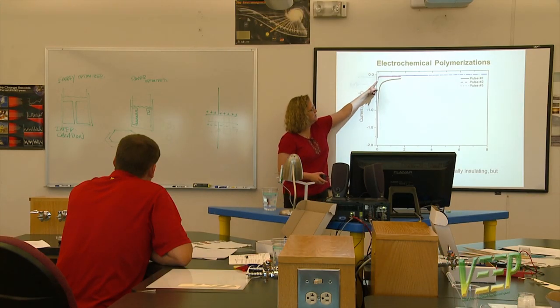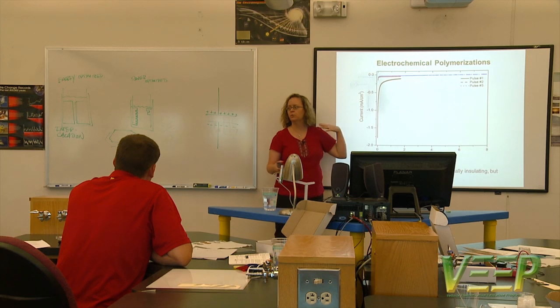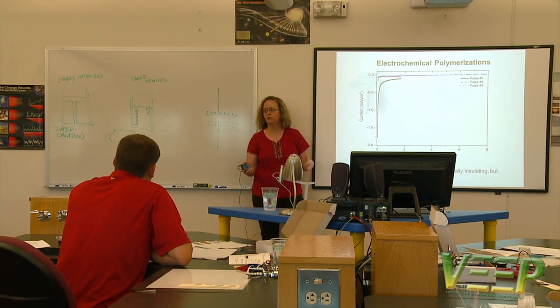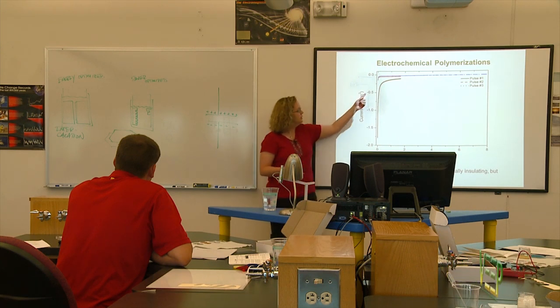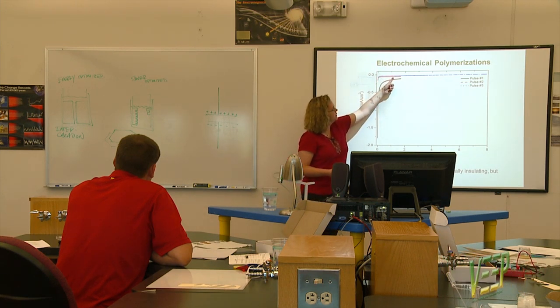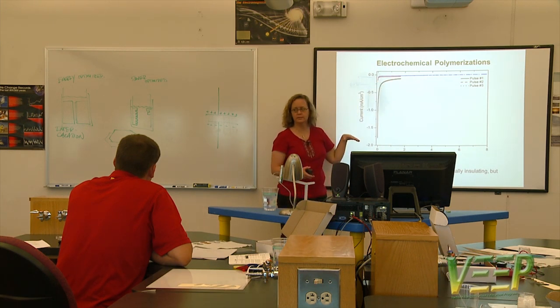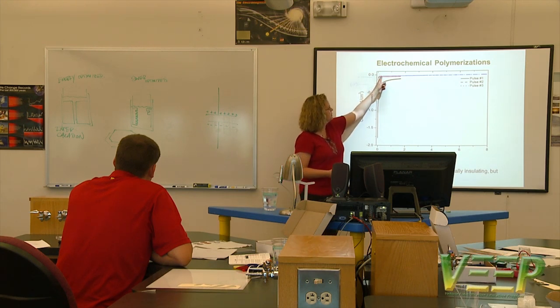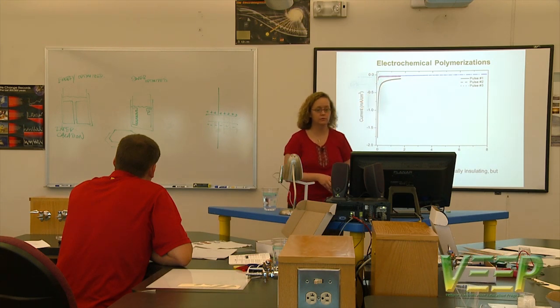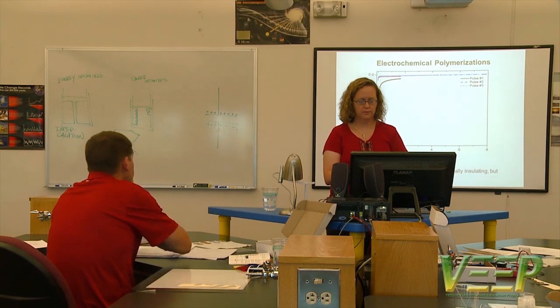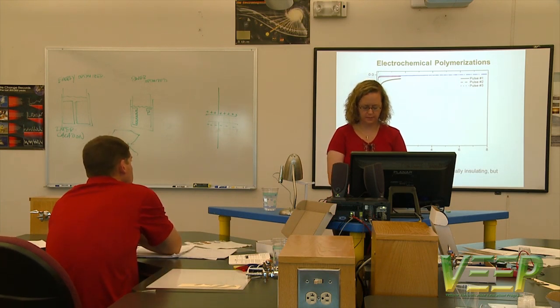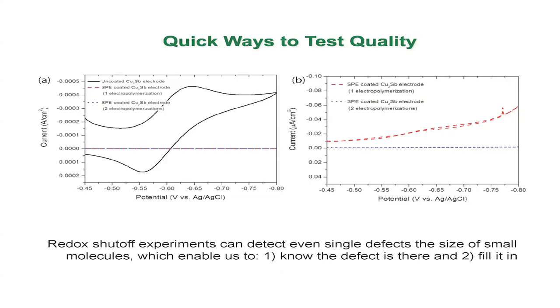So the second pulse is in red, and you see that the current started really low because most of that structure was covered already and no more polymer could grow there. So it can only grow where there are bare patches. It approaches zero pretty quickly. Then we let it rest, and then we do a third pulse, and the current's really low. So that tells us it's pretty good, but it doesn't tell us it's perfect.